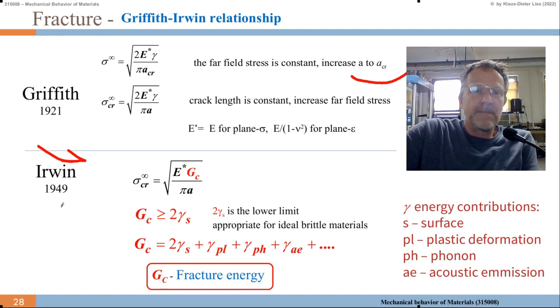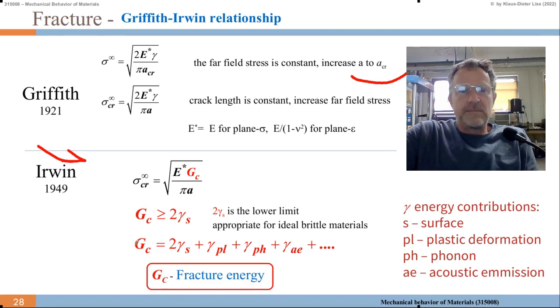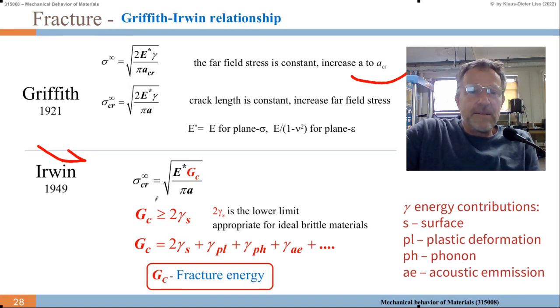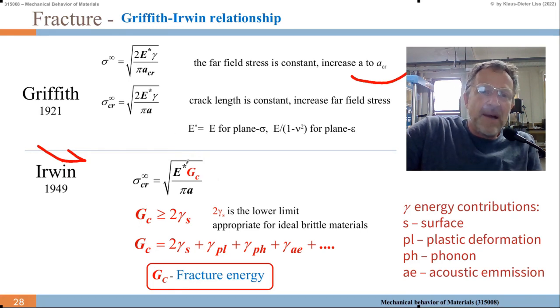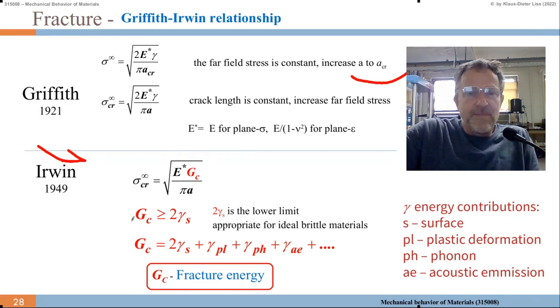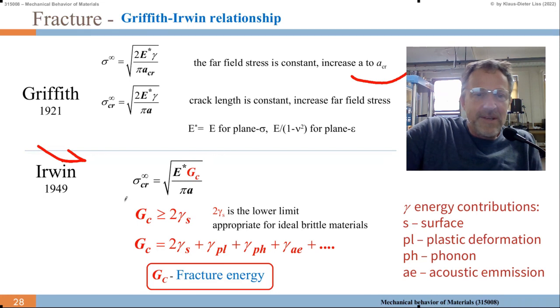Now Irwin came in 1949. He said the critical stress equals the square root of E star over pi A times GC. So instead of gamma, he put GC, which is a constant I call the energy release rate.